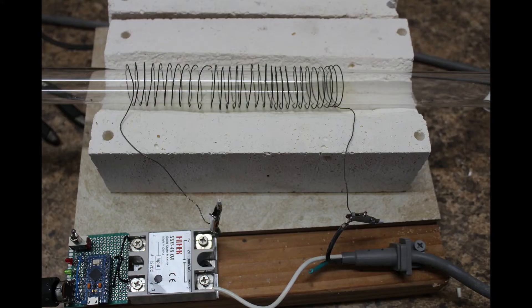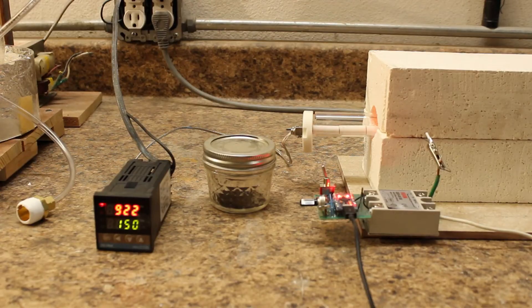I used a tube furnace I constructed out of two alumina silica fire bricks, a fused quartz tube, and some nichrome wire to heat our substrate.